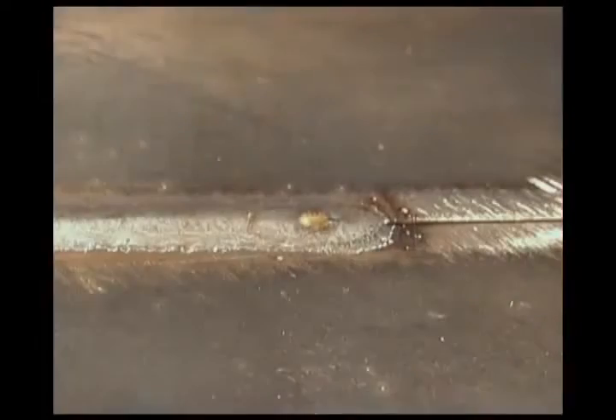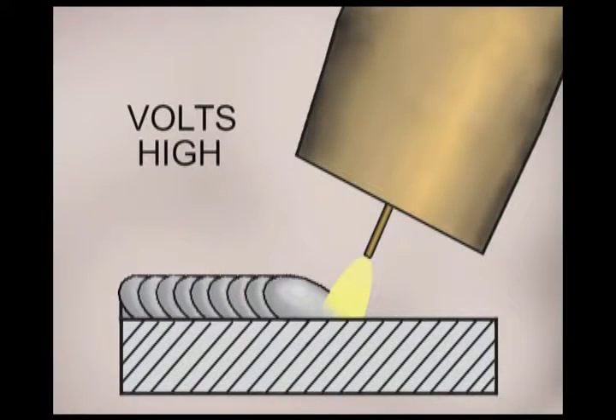Once the wire speed is set, the voltage is adjusted to produce an optimum stable filler metal transfer. The molten weld puddle should flow out to the sides and be very controllable, with the finished weld bead virtually spatter-free. If the voltage is set too high for the wire speed, the length of the arc is increased, putting more heat on the molten weld metal. The puddle is more fluid and agitated, making it difficult to control and causing excessive weld spatter.